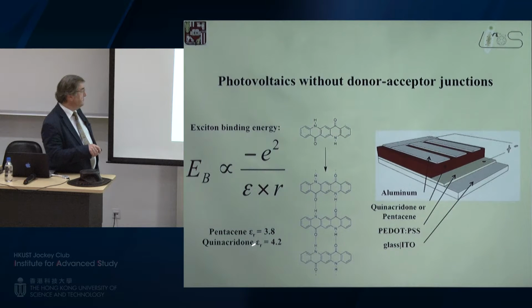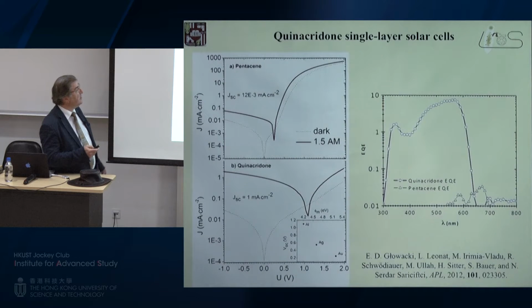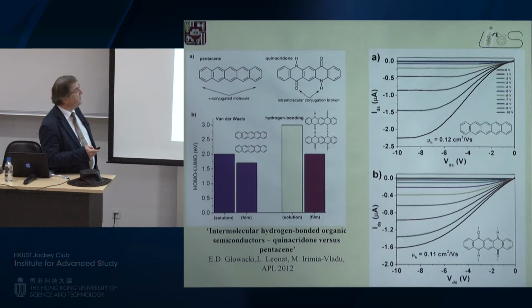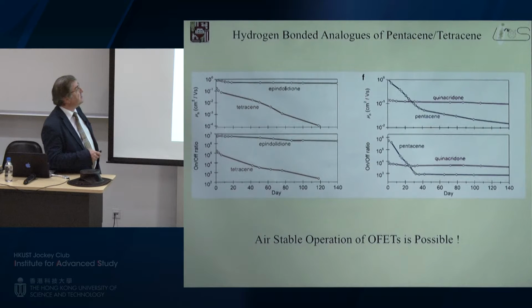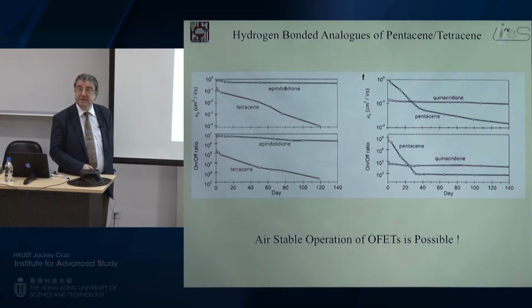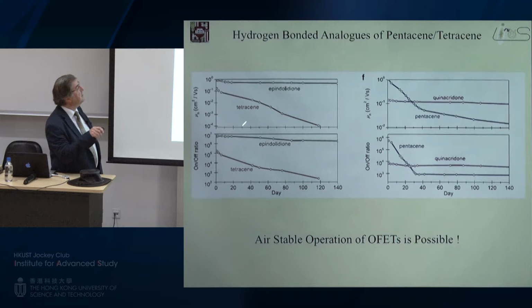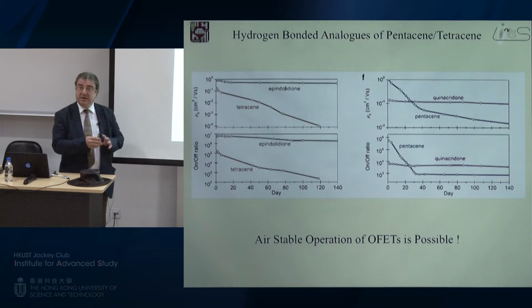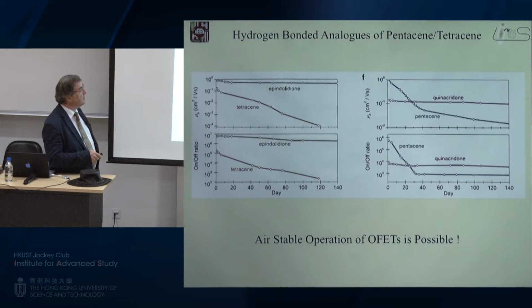And it has a very nice, basically higher dielectric constant. We can make diodes out of it, and you can get nice photo effects, solar cells, even from a single layer of quinacridone, you can get nice photo effect. But this is the most important thing. Look at the transistors made from pentacene, made from quinacridone. Identical conditions, identical setup, and look at the stability. Indeed, tetracenes and pentacenes, they are really dying on a matter of, let's say, a couple of days. And the quinacridones, epindolidiones, are very, very stable. These are in air without any protection, constant operation.